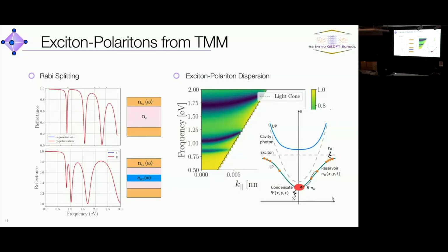And that's why exciton polariton got popular, because what's happening here is the following. If you have an exciton, the dispersion of the exciton alone is flat, at least on this scale. But in reality, it's a parabola of a free particle, and it has a mass. But the mass is related to the curvature of this line. So you can tell that the mass of this line is definitely larger than the mass of this other line. Now, if you do Bose-Einstein condensate theory, you will see that the condensation temperature is inversely proportional to the mass. And a smaller mass leads to a higher condensation temperature.